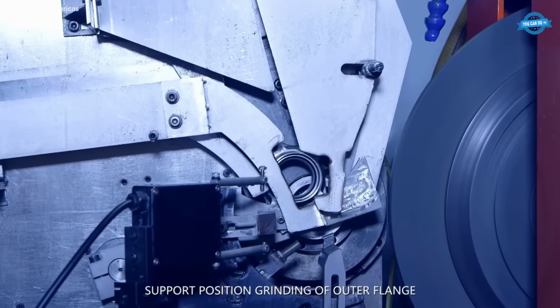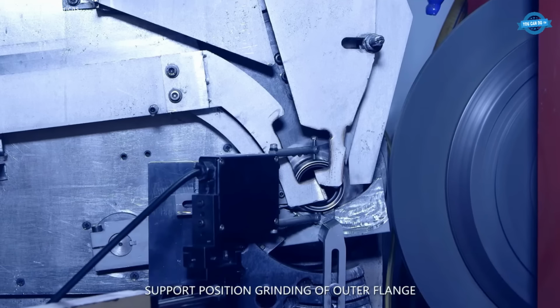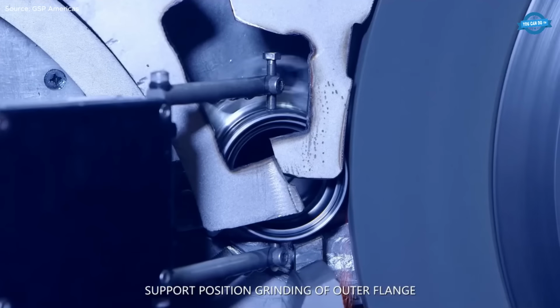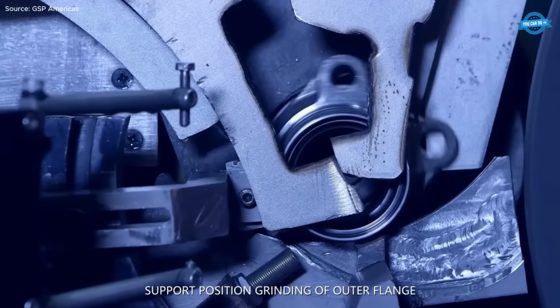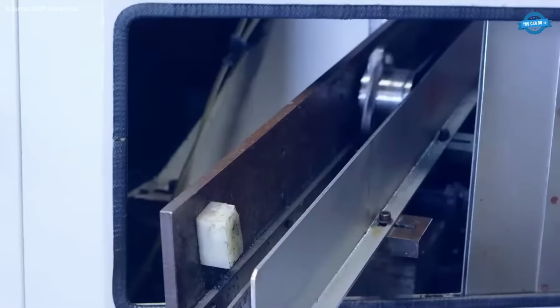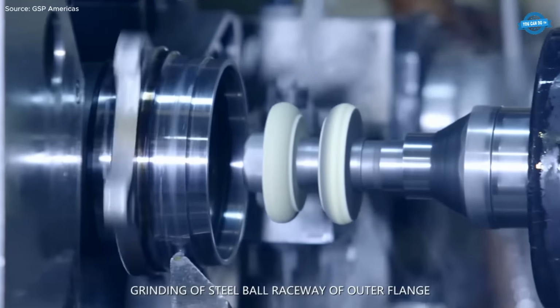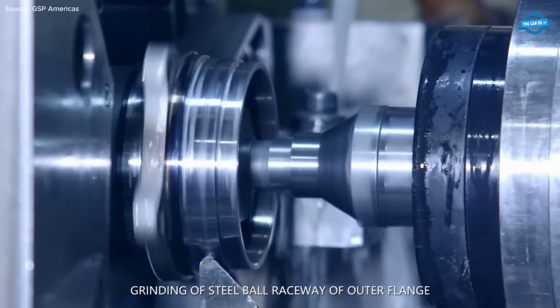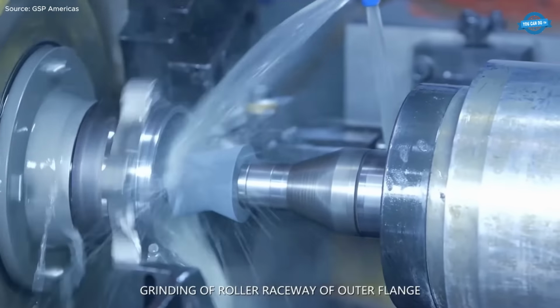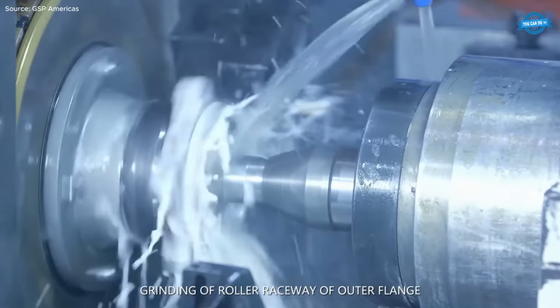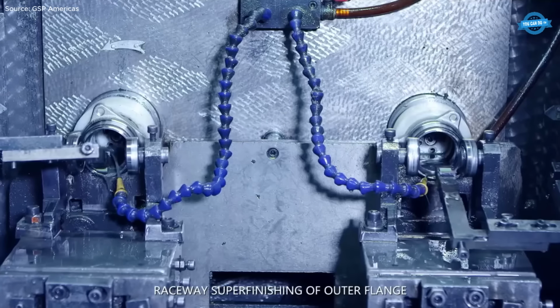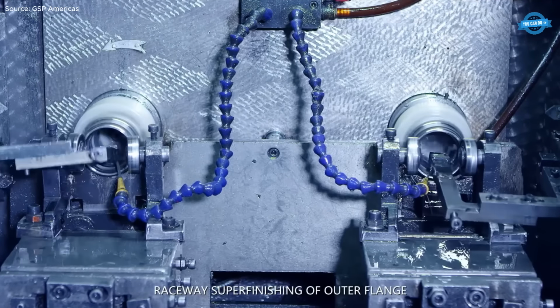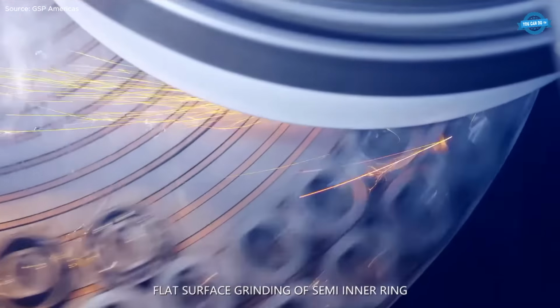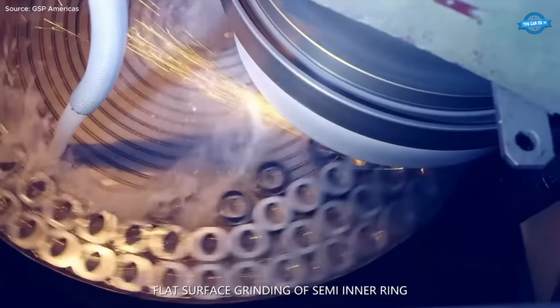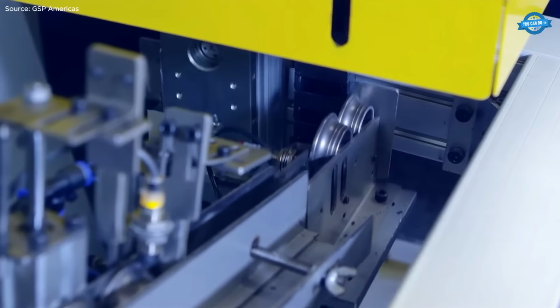After heat treatment, the outer flange is subjected to final lathing to restore dimensional accuracy. Drilling operations create mounting and fastening features, followed by support position grinding to ensure concentricity. The steel ball raceway and roller raceway on the outer flange are ground with high precision, then superfinished to reduce surface roughness, improve load distribution, and extend bearing service life.